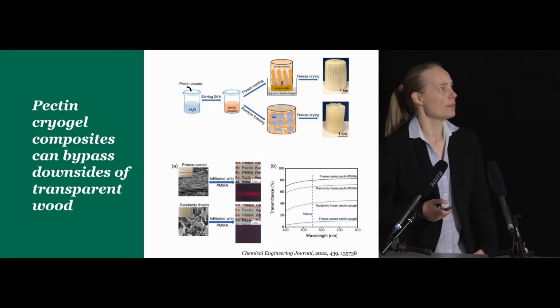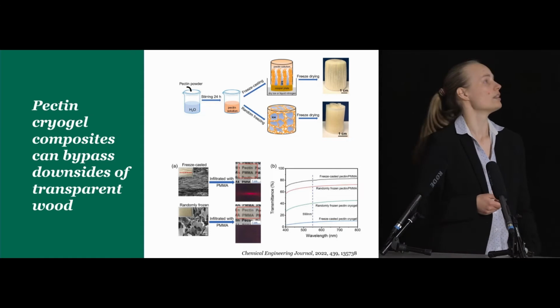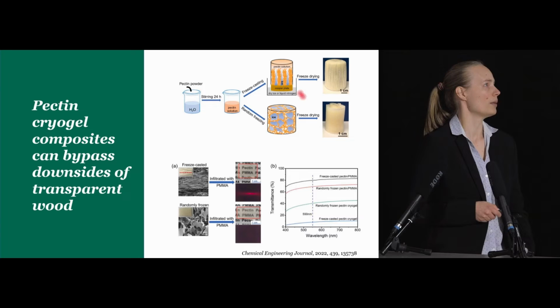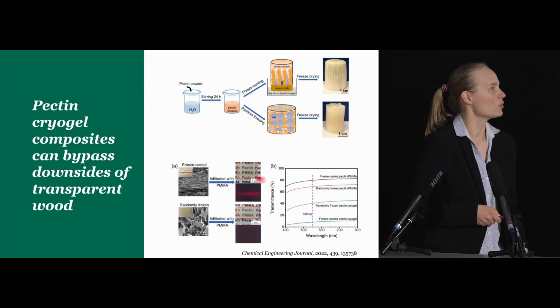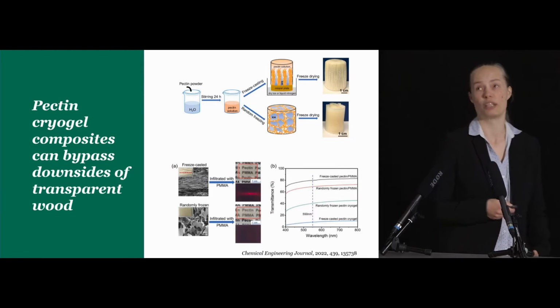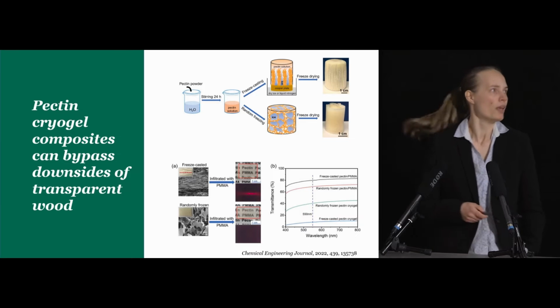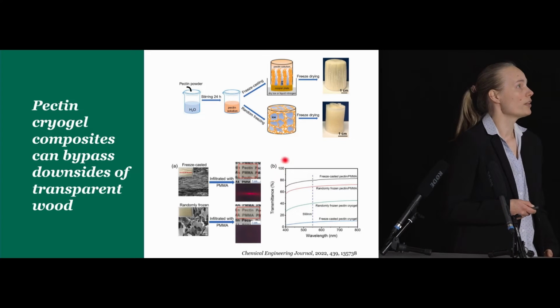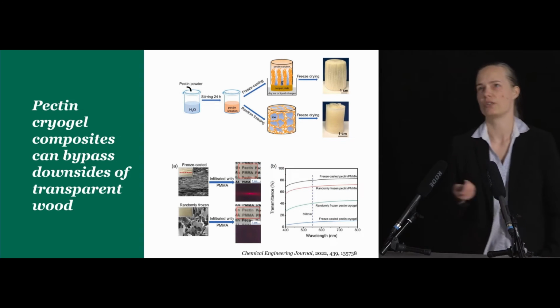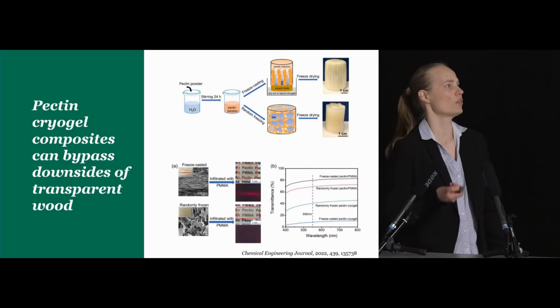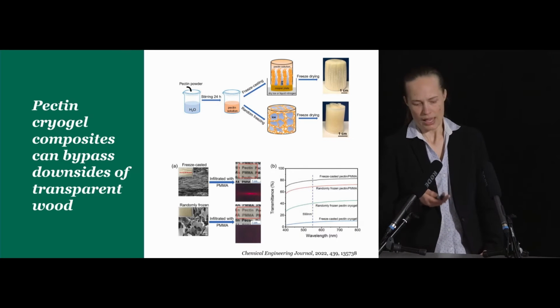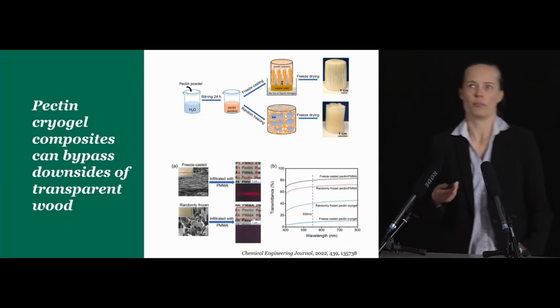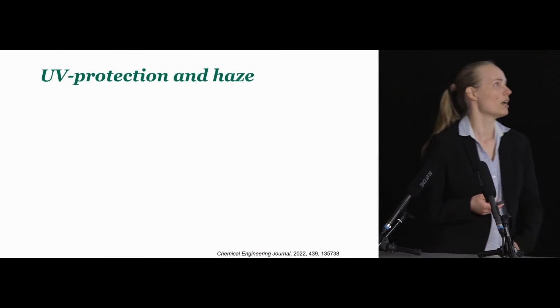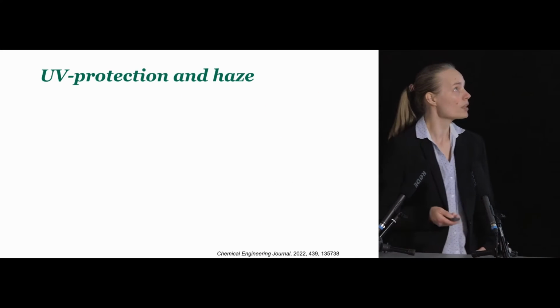So we took those templates, and then we filled in or impregnated them with PMMA, and we got a composite that actually looks a little bit like transparent wood. What's maybe the most noteworthy thing is that it's transparent over all the critical wavelengths that we want for our photonic devices. And in addition, by using pectin, we could get some added benefits.